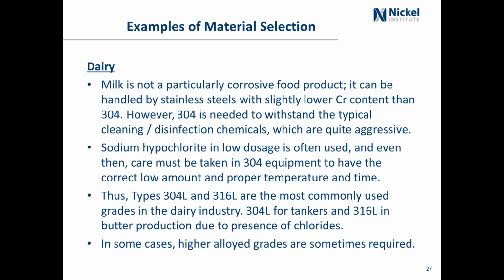Milk is not a particularly corrosive food product. It can be handled by stainless steel with even lower chromium content than in 304. However, 304 is the minimum to be able to withstand the cleaning and disinfection chemicals, which are much more aggressive or corrosive than the milk itself. In some cases, cleaning might be done with sodium hypochlorite in low dosages, but care has to be taken because sodium hypochlorite is an extremely strong pitting agent. And if you leave it in contact for too long, you could cause pitting corrosion of the 304 stainless steel.